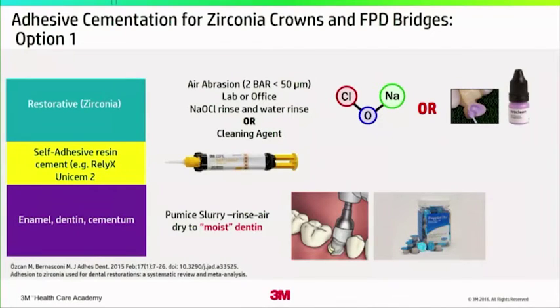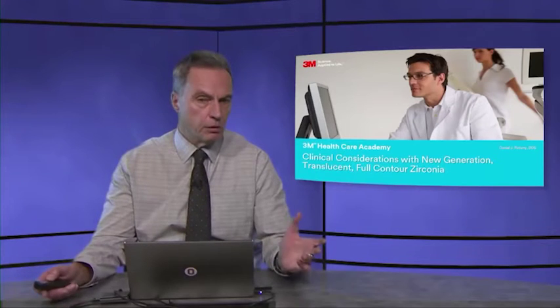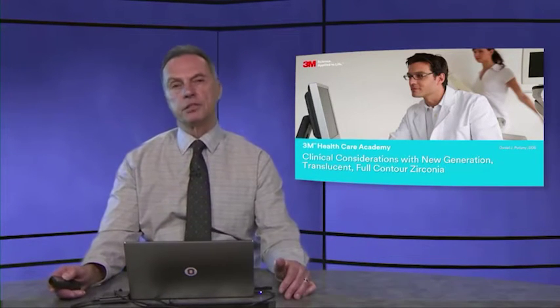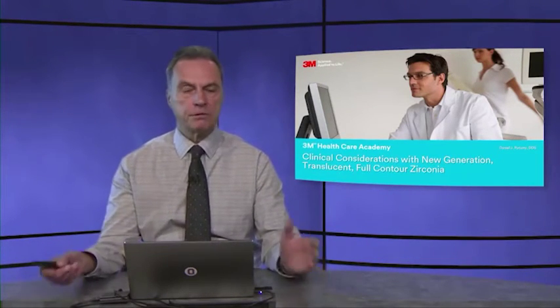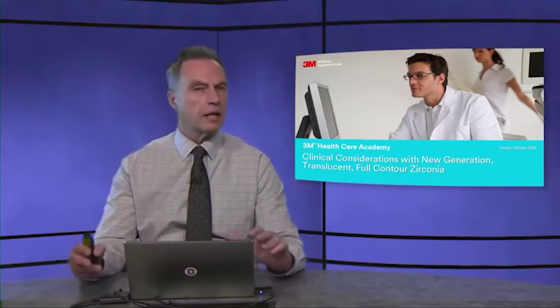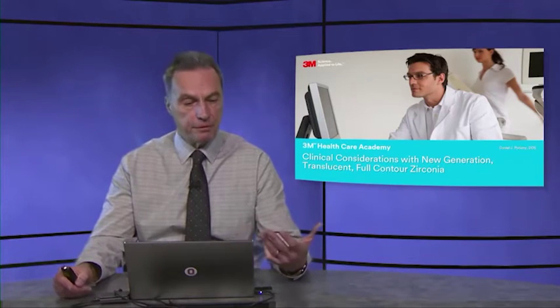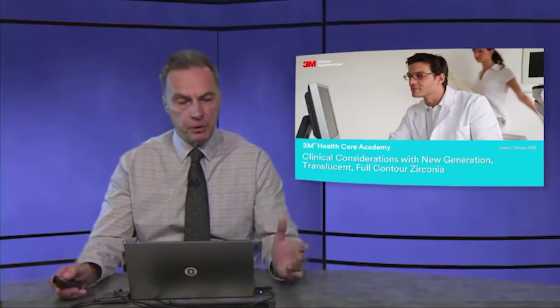Now, RelyX Unicem 2 has been around for quite a long time. It's actually the first cement developed in this category. And in that sense, you are going to get a very strong bond to this material. And again, if you want to adhesively bond, this is my go-to for literally 90% of everything that I do, unless you run into the situation in a severely over-reduced or over-tapered restoration, not a lot of quality tooth structure to bond to, you may want to consider the highest level of adhesion you could get from a high-performance system.